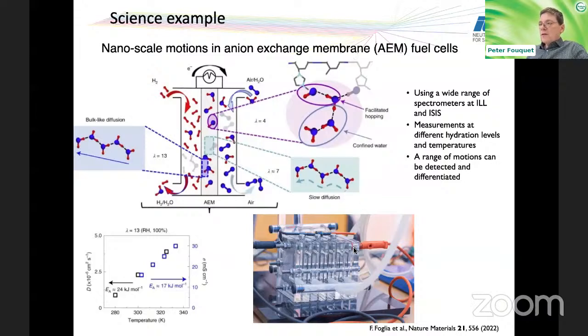And the interesting part of this is that you can really look at the polymers themselves, and they specifically built fuel cells for the neutron experiments. And by combining the different spectrometers, you can get a huge range of dynamics, easily 9 orders of magnitude apart. And by separating them out, by changing the temperature and by changing the relative humidity, you can really distinguish the different motions and get a lot of experimental information that's otherwise only available via calculations, molecular dynamics or DFT.